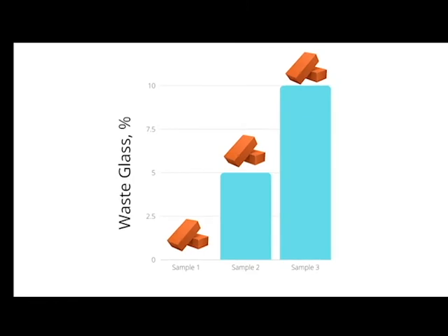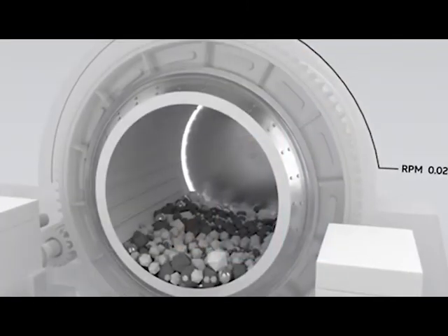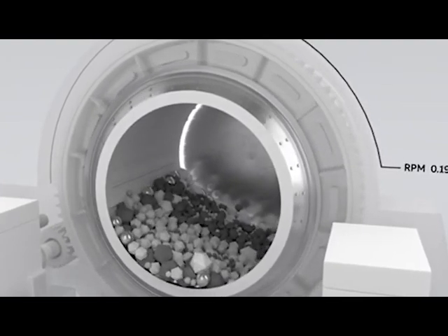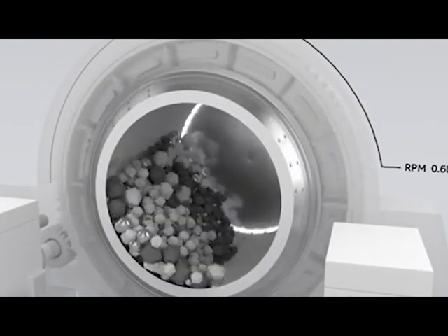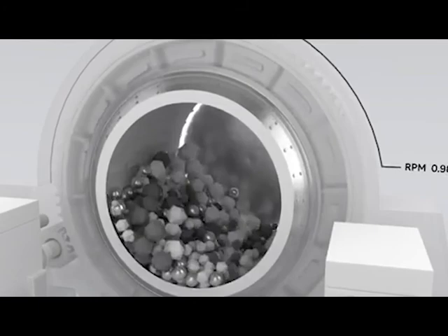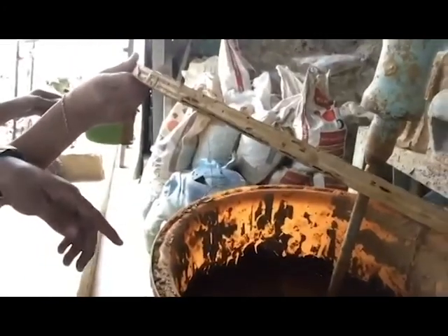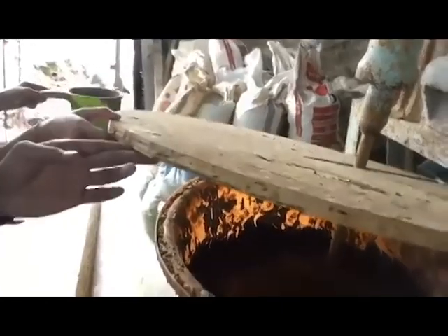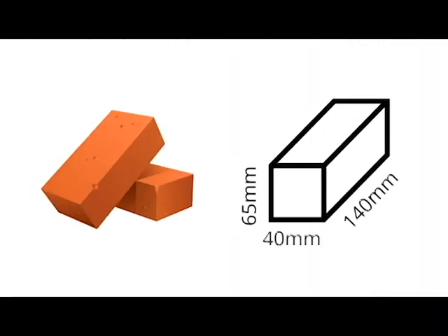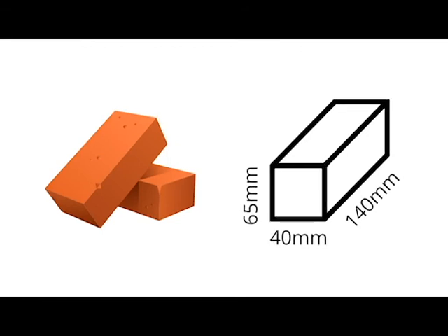In order to compare the clay brick and bricks made of clay and glass, each batch of specimens were mixed in a porcelain ball mill to ensure homogeneous mixing. Then, 20-25% of water was added and mixed to obtain the plastic condition of mixture. Soft mud rectangular clay bricks with dimensions of 140 mm, 65 mm, and 40 mm were formed using brick hand molding.